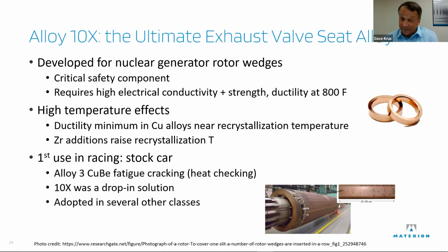I haven't seen a lot of the cracking issue, but it also helps because of retaining its strength. It helps to avoid valve seat recession. And there is nothing with this kind of conductivity, and you need thermal conductivity in the exhaust valve seats to get the heat out of things like the exhaust valve bridge, right, to distribute the heat, get it out of the head of the valve. Nothing with this kind of ductility has that elevated temperature property set.